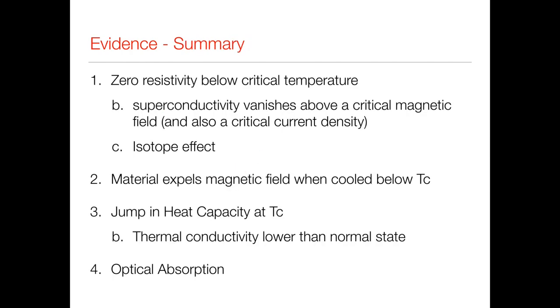Okay, just to review the evidence: zero resistivity below a critical temperature. But that superconducting state vanishes above a critical magnetic field. It's also the case that there's a critical current density. If you're in a superconducting state, there's a limit to how much current you can carry before you destroy the superconducting state and you go back to normal. That's perhaps not too surprising given that if there's a current, that also creates a magnetic field. So those things are kind of linked together.